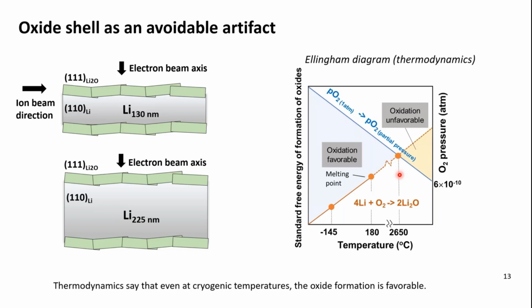So we believe the oxide shell came from the residual oxygen gas in the PFIB chamber. To calculate this, we borrow some concepts from the Ellingham diagram, where you can predict at what temperature the oxidation is thermodynamically favorable or not. We know the partial pressure of the oxygen in the PFIB chamber, and we know the temperature, so we can calculate it.